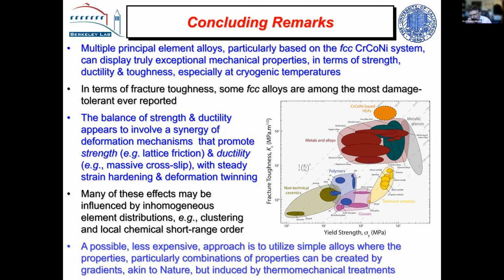But in a high entropy alloy, you've got 3 to 5 different elements. So every slip band is not quite the same. And some may be harder to form than others, right? And so there's evidence that instead of twins simply amalgamating to form bigger twins, which you see in a lot of traditional alloys, you get multiple twins formed everywhere, and they don't grow as much. So you've promoted nucleation because you haven't got a uniform sort of slip band. This is a notion that's been pushed by our former postdoc, John Ding, and he's done the MD calculations on that, and it does seem to suggest that's the case.